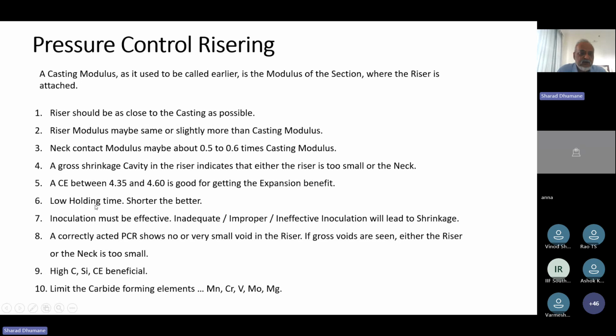Low holding time. Why holding time is important is because it is the most critical parameter, the condition which affects the melt quality. I think this is something which many of us are not fully or seriously aware of, because holding time is where a well-made melt gets deteriorated. So when does holding occur? When your molds are not ready, you are waiting. You have a first spectral sample asking for some additions. We made those additions, then sent back the sample. The second sample result is coming, and we are holding the furnace.